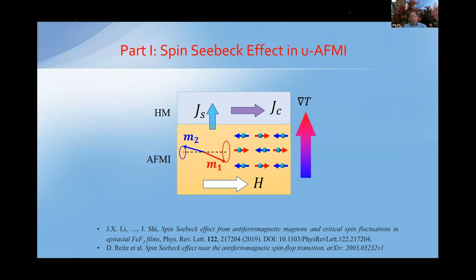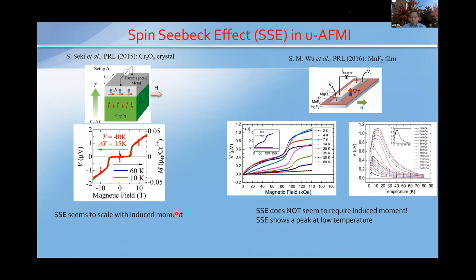The first part of the experimental work is the spin Seebeck effect. As I said, we want to generate antiferromagnetic spin current from incoherent magnons in these uniaxial antiferromagnets. These are the two relevant papers that I will mention. Before our work, in 2015 and 2016, these two PRLs were published on chromium oxide and manganese difluoride.